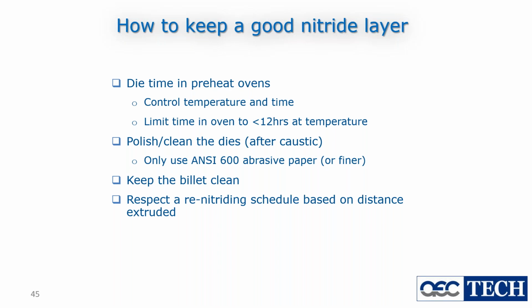So with all that information, and with a good nitrider and computer control, you can really do a good job nitriding the die. But I hope we've shown you as well that if you don't control the time that the die spends in the preheat oven, it doesn't matter how good a job you did nitriding it, you've destroyed it by leaving it in the preheat oven.